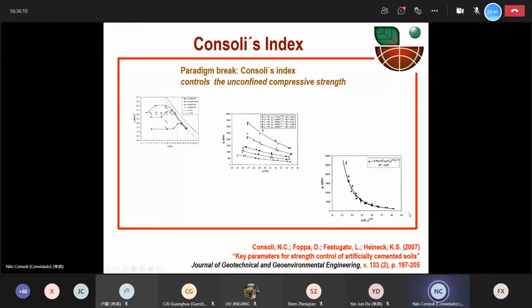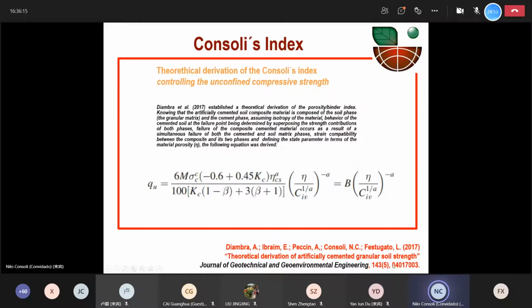It's a power function. But then in 2017, in a joint work with University of Bristol, we have carried out and we have shown through a theoretical derivation the capacity that we have of this index, that really shows that the porosity and the volumetric cement content really controls the strength of it. So that was published, as we can see here, in this reference that we have just below here.